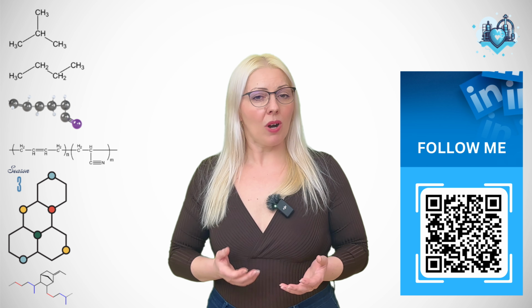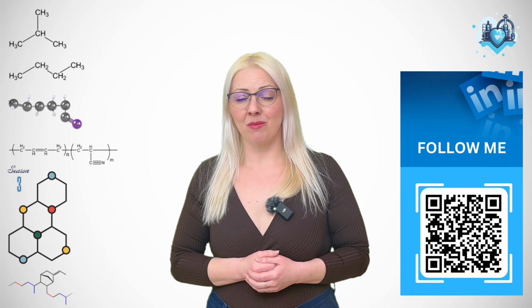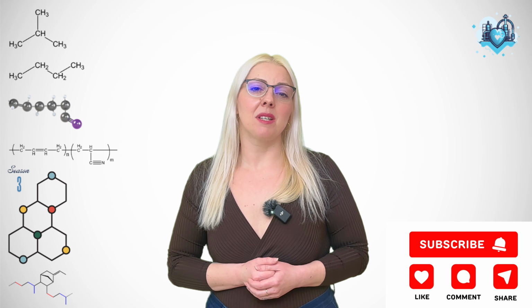That means scorch safety margins shrink, silane reactions accelerate, oxidative processes increase, and small control errors become amplified. So the summer strategy becomes this: control the temperature ramp, avoid unnecessary early high rotor speed, watch cooling efficiency, protect silica from humidity, respect shorter thermal safety margins. Your compound did not change. The physics did. And when you understand that viscosity decreases exponentially with temperature, while reaction kinetics accelerate at the same time, summer variability stops being mysterious.